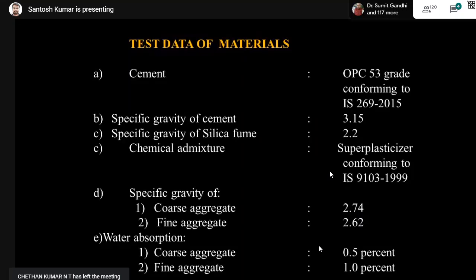Coming to the data, specific gravity of cement is 3.15. We have to perform this test. In most cases I see the cement specific gravity is assumed to be 3.15. No sir, the specific gravity of OPC cement varies from 3.05 to 3.15, or sometimes 3.03 also. You cannot directly take cement specific gravity as 3.15, because specific gravity plays a major role in your concrete mix proportioning. So, specific gravity of cement shall be determined using Le Chatelier's flask. Specific gravity of silica fume will be around 2.2.